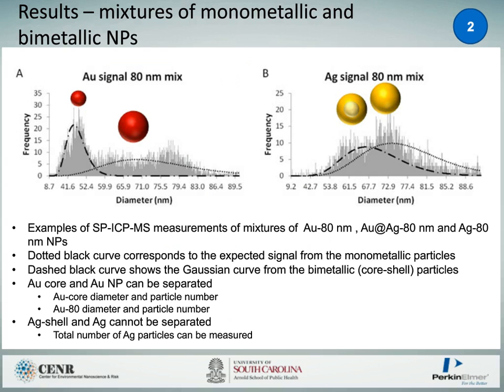So here we're looking at results, mixtures of monometallic and bimetallic nanoparticles. You can see that on the left-hand side we have the gold signal, on the right-hand side the silver signal. The dotted black curves correspond to the expected signals from the monometallic particles, and the dashed lines are the expected signals from the bimetallic particle.